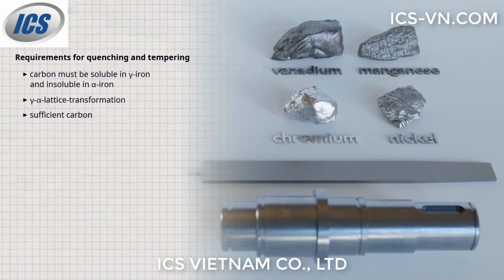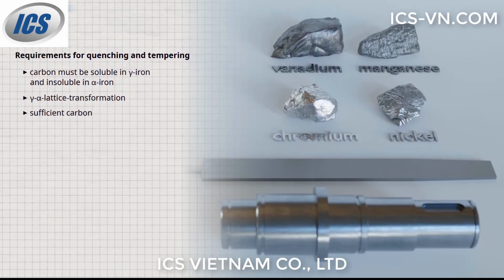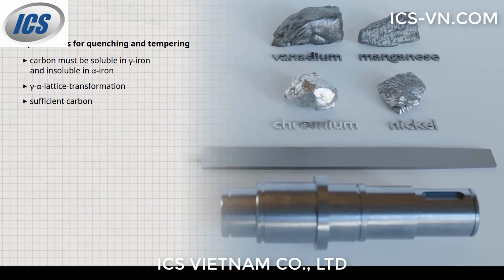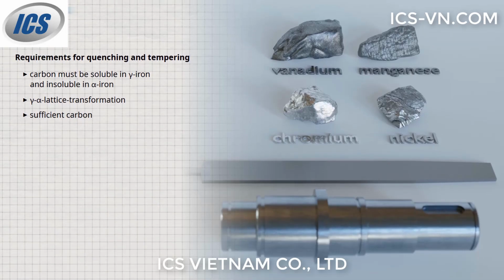In some steels, such as the stainless chromium-nickel steels, the gamma-alpha lattice transformation is prevented by the addition of alloying elements such as chromium and nickel.